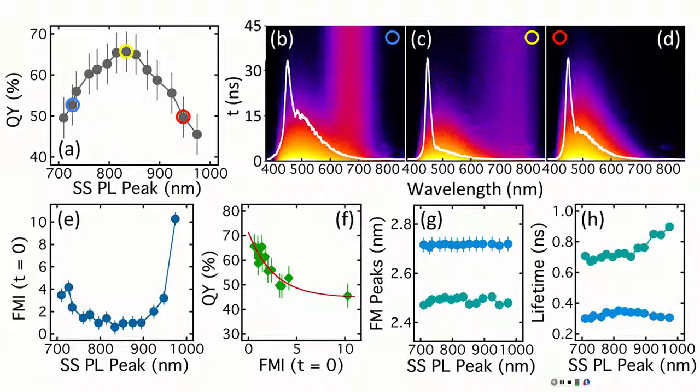And it's not emissive probably at all. Probably dark states anyway for this. Well, that's the question. Why is there emission? No, it's not coming from the ligand itself. It comes from a surface of the quantum dot as a defect, which is more localized. It's really localized on a few atoms of the silicon, but not spread over the entire system as bulk.